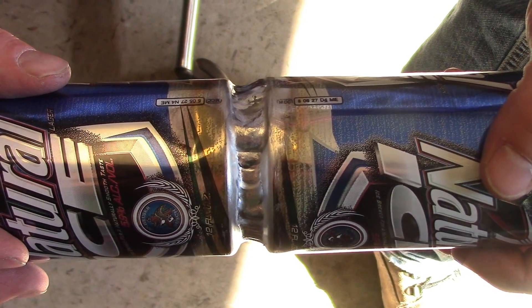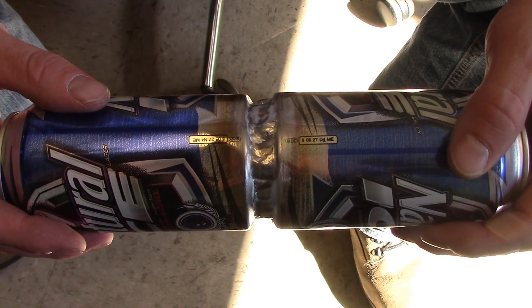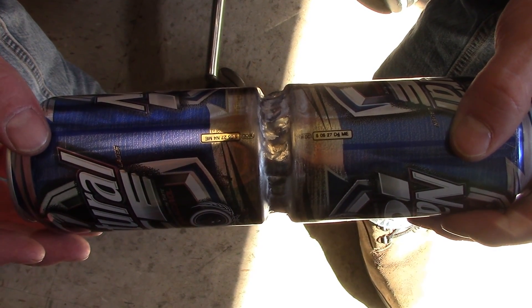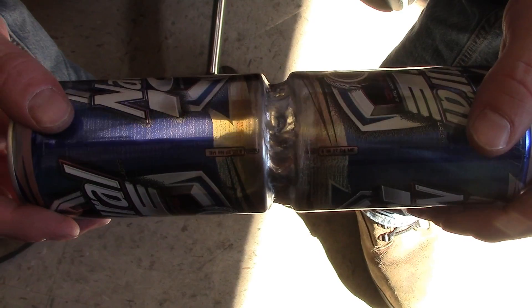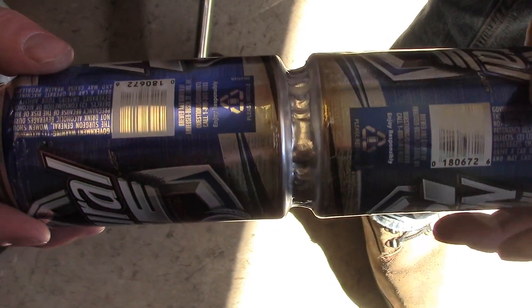This is the first one we did. We started with the old Natty Ice can, and we discovered — when we rinsed it out — that steam was forming when we started, so we had a little bit of a glob in the start. But we got her to fuse, and once we got it to fuse it went pretty smooth.